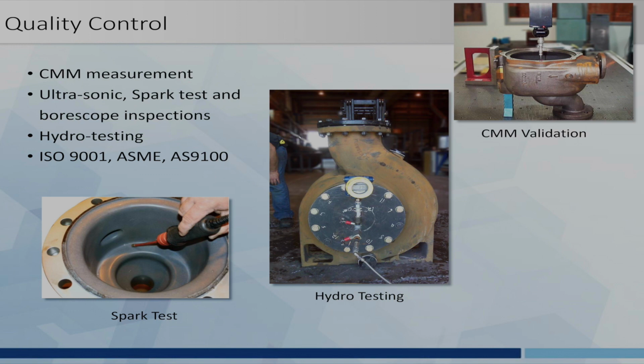For quality control, we do have a CMM measurement. Sometimes there are some very critical dimensions that we need to double check. We do ultrasonic thickness reading. We do spark testing. Sometimes we have to borescope to see inside and make sure that visually there are no bubbles and flaws. We can do hydro testing. We can do that to the metal before, and we can also hydro test after it's been lined.